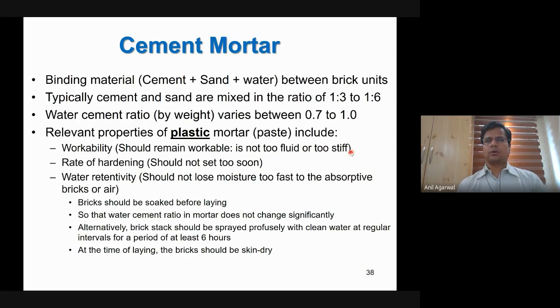So the way it is done is that before you start laying the bricks in a wall, you soak them in water, you dip them in water, you let them be there for half an hour, 1 hour, and then you take them out, so that at least from outside the brick is completely wet. Then you clean the surface dry so that the surface is not wet, because if the surface is wet, that means as you add the mortar, it will add water to the mortar, which is a bad thing.